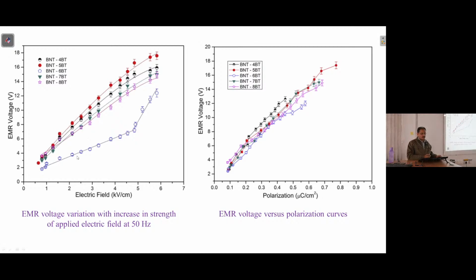So now if you consider, both the lines actually have distinctly different slopes, right? This one has a lower slope, but this one has a steeper, higher slope, right? So here we can consider this point precisely as the transition point. As you increase the field from here up to here, the increase in the output, which for our case is the voltage, is linear but at a slower pace. But beyond this, if you start further increasing the voltage, then a steep curve is obtained.